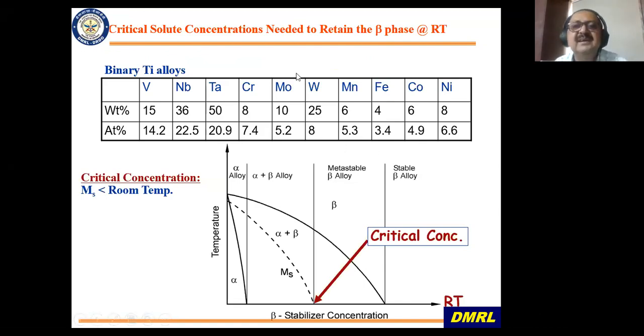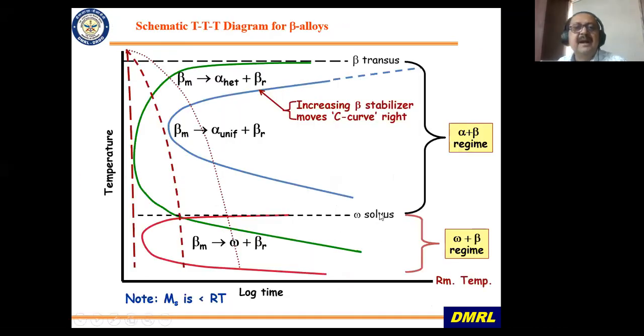Again, these are the weight percentages of elements which can single-handedly retain the beta phase. You can see iron is a very strong beta stabilizer. The amount required to stabilize the beta phase at room temperature is much lower as compared to other elements. So beta alloys are on this side of this phase diagram. First you have the metastable beta alloys and then the beta alloys.